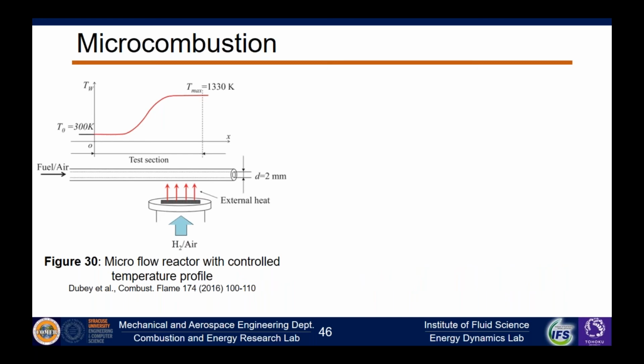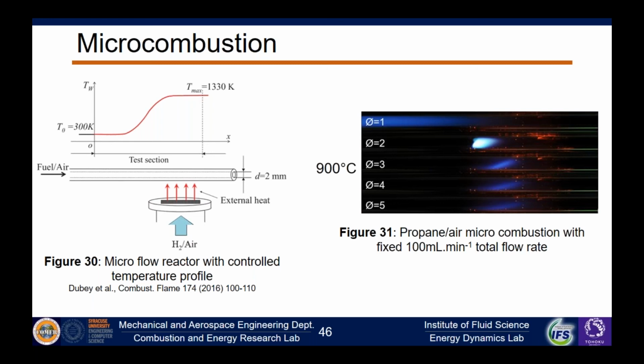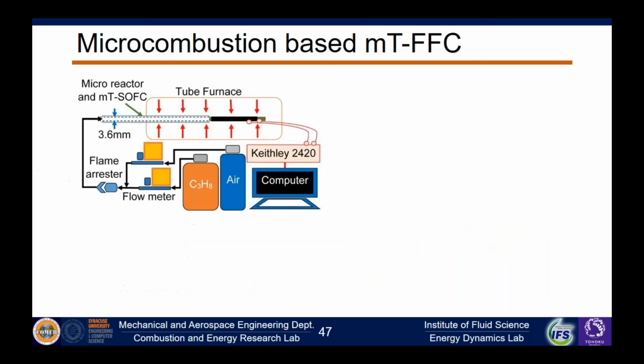To do that, we use a simple setup. This is actually from Maruta's group, an experimental setup they developed. Again, this isn't a full self-sustained system. Essentially, they take a quartz tube with an internal diameter of less than 2 millimeters. They preheat the fuel and air with an external heat supply, which mimics the idea of recirculating the heat to preheat the fuel and air. You notice the temperature of the incoming fuel and air increases, and you can stabilize it at a certain point, depending on the combustion characteristics. By doing that, we stabilized our maximum wall temperature at 900 degrees Celsius, and now we can sustain a flame even at an equivalence ratio of 5. So no longer 1.4; we can push well beyond that initial equivalence ratio.